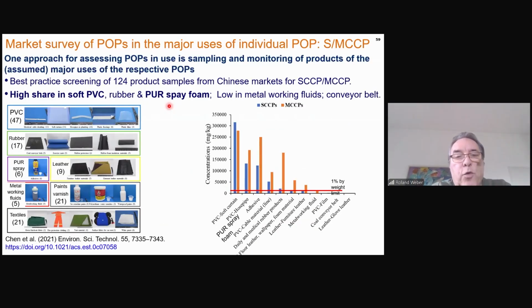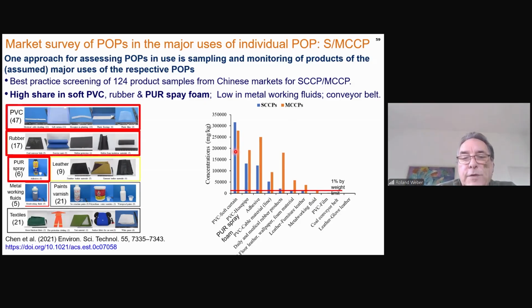And I give you a few best practice case studies here for materials. Here I was involved from Beijing University. We screened 124 products on the Chinese market. A high share of the soft PVC, and 50% of PVC is finally going into building and construction, and a large share of the polyurethane foam spray, which fully goes into construction, contain very high levels of short chain and medium chain chlorinated paraffin, up to 50% of the product. And the same was found in Europe.